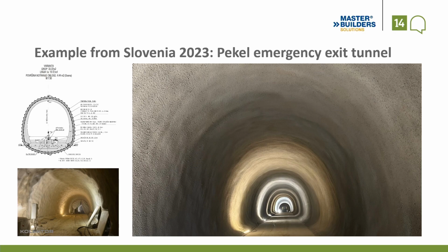The Pekel emergency exit tunnel, originally designed with 300 millimeter cast concrete, was changed on short notice, thanks to the owner and the designer, to a spray applied membrane and spray applied inner lining. You see the application they already applied, spray applied waterproofing at the bottom. And this is how the tunnel looks at the very end. It's rough, you have to live with it. But it did the job.